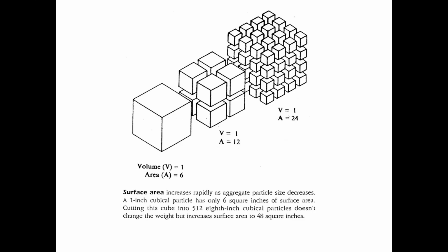All right, if we subdivide each of those particles in all 3 dimensions, then we end up with the third figure. We still have 1 cubic inch of material, but now we have a surface area of 24 square inches. So our surface area has quadrupled, and we're just now getting to the dividing line between coarse aggregate and fine aggregate. Each of those aggregate particles is about 1/4 of an inch, which is the dividing line, that number 4 sieve. So we would have to subdivide these particles yet again just to get through the doorway of a fine aggregate. So the purpose of this figure is just to highlight to you that the finer a material gets, the more surface area that we have to coat with our cement and water paste. And it's not just a slight increase in surface area, it's a multiple increase in surface area.